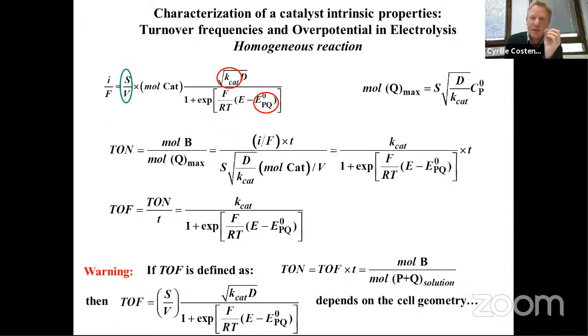And of course, if you want something that is intrinsic to your catalyst, you have to remove this dependence of the current on this cell geometry parameter. And this is obtained if you divide the current, which gives you the number of molecules you produce per unit of time, by the number of molecules in the diffusion reaction layer. As you can see here, if you define the turnover number and then the turnover frequency this way, you obtain an expression of the turnover frequency that is independent of the cell geometry and is only specific to the characteristics of your catalyst, which means its standard potential that will control the overpotential, and the catalytic rate, which will give you the efficiency of the homogeneous reaction.